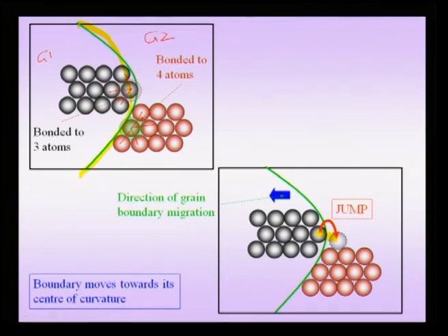This atomic jump automatically means that my boundary, which was originally my green line, has now become a new boundary that has formed here, and the overall process can take place in such a way that the grain boundary can migrate from right to left. This will happen when more and more atoms jump from the right direction to the left direction, becoming part of grain 2, and in the process the grain boundary sweeps from right to left, and overall this will lead to the grain on the left shrinking and the grain on the right of course growing.